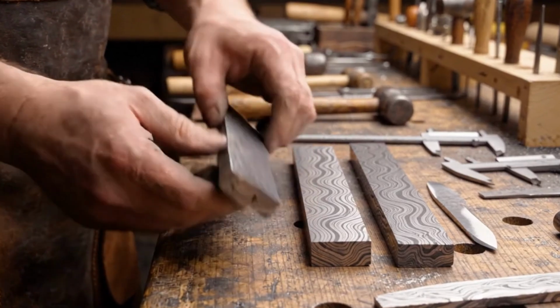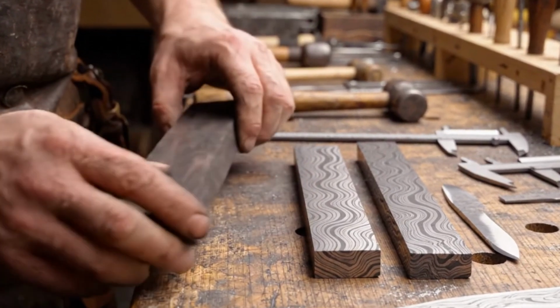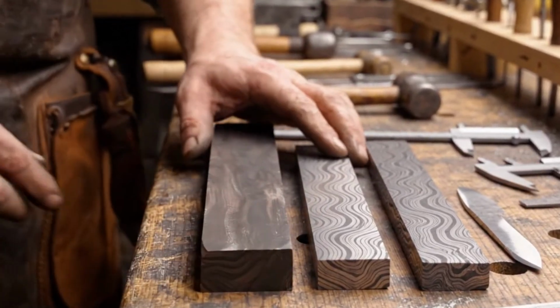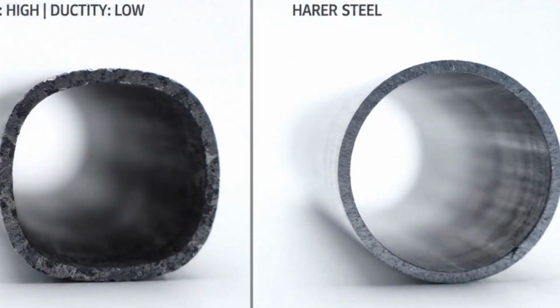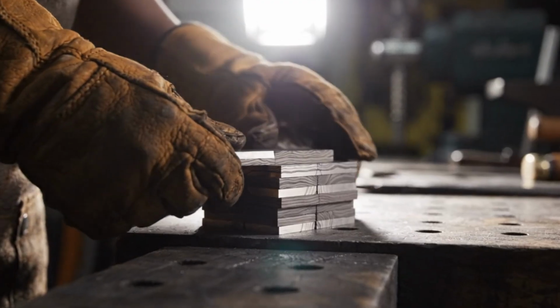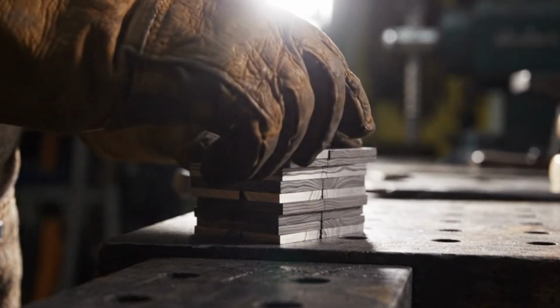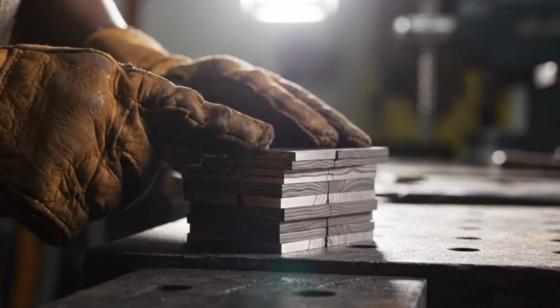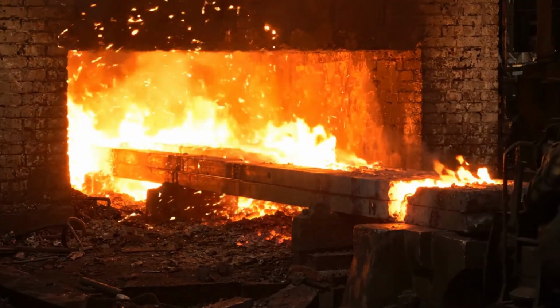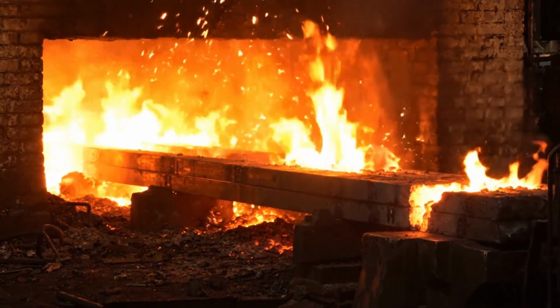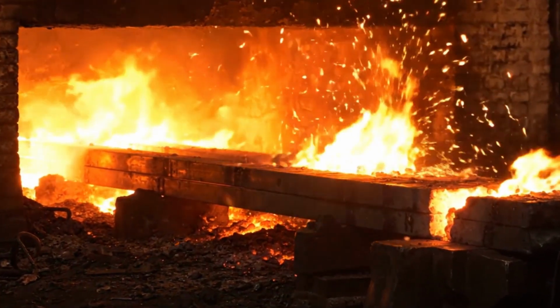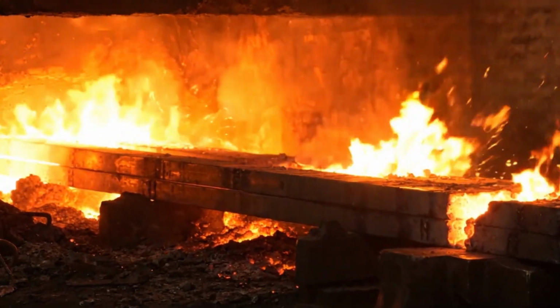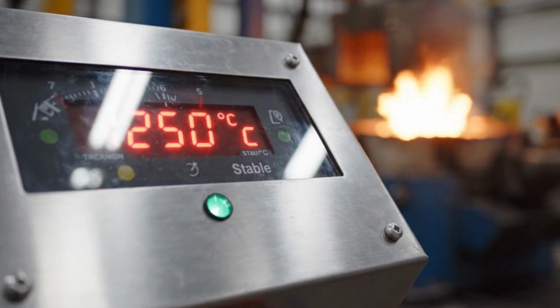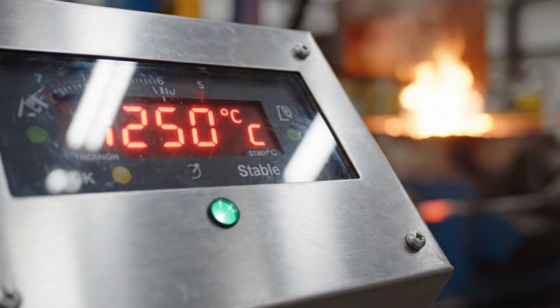The process of pattern welding itself is a highly skilled art form that requires immense patience and precision. A blacksmith begins by selecting specific types of steel, each chosen for its unique properties. For instance, a high-carbon steel might be selected for its ability to hold a sharp edge, while a softer, more ductile steel might be chosen for its flexibility and resistance to shattering. These different steels are then stacked in alternating layers. The stack is heated in a forge to a temperature where the metals become plastic enough to be welded together under pressure, but not so hot that they melt and lose their distinct layers.